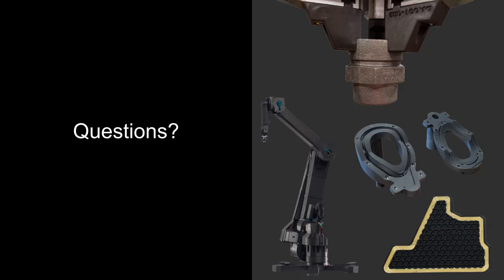So a good question from William. You described the failure of carbon fiber reinforced parts as sudden and catastrophic, while Kevlar reinforced parts have a more gradual failure. Does that imply that a Kevlar reinforced part could have partial damage that is not very evident? So I would actually argue the opposite. Kevlar, once it's starting to damage, begins to deform. And you'll be able to see that deformity if you're really starting to get it towards that maximum load. That actually makes it easier to see once it starts to degrade, because the fibers one by one start to fail, and it starts to deflect a little bit more. Whereas carbon fiber barely deflects at all. When carbon fiber breaks, it's at about 1% deflection before it snaps. So although it has a very, very high strength, it fails pretty immediately when it does fail.